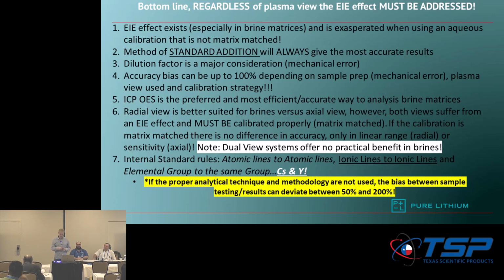ICP-OES, and we have done a round robin. We've sent them all out by XRF, ICP, ICP-MS spec. You just get the most consistent numbers off an ICP-OES for my industry, for what we're doing. A radial view is definitely going to make your life much, much easier. So if you have the sensitivity and you don't need to push the sensitivity, I cannot stress enough, you will be in a much happier place if you stick with radial and avoid axial. However, axial will work. Just make sure you're using the right internal standards.